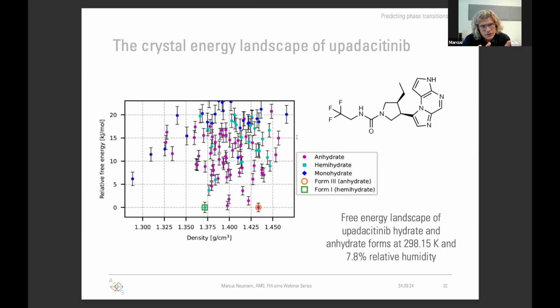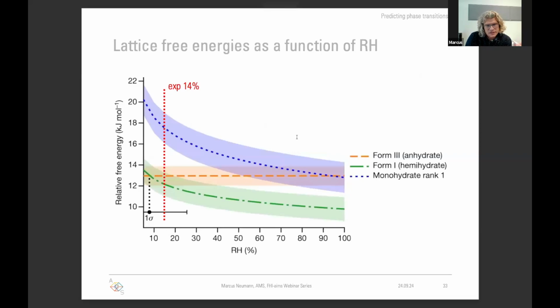And so here we use this example to show free energy dependence as a function of relative humidity. That is this plot. So again, the error bars have now turned into bands. We can express a 1 sigma error interval for the expected phase transition. Here the phase transition is between an anhydrate and a hemihydrate, and that phase transition is truly observed. It is observed at 14% relative humidity. So this is within the 1 sigma error interval.